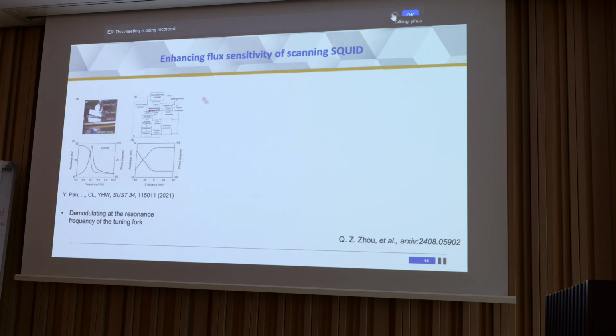But we still face one challenge in measuring the fractional vortices, which is that the flux of fractional vortices is very weak when the temperature is very low, meaning it's far away from Tc. And we have used this technique, which seems to work quite well: we put our scanning SQUID chip on top of a tuning fork. Since the tuning fork has a resonant frequency on the order of 10 kilohertz, we can lock into this frequency to demodulate the flux at this frequency so that it acts as a vibrational oscillator, so that we can get even higher flux sensitivity.